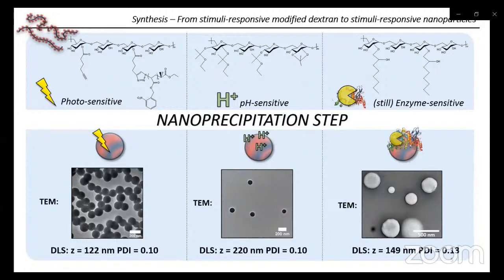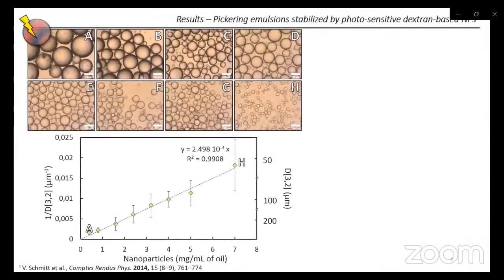In these three cases, you can see that we obtained well-defined spherical nanoparticles with sizes ranging from 122 to 220 nanometers and a quite low PDI. So then I will describe more specifically the results we obtained with the photosensitive nanoparticles and specifically with the stabilization of Pickering emulsions. In these pictures and on the graph, you can see that the higher the amount of nanoparticles, the lower is the size of the droplets we stabilized.